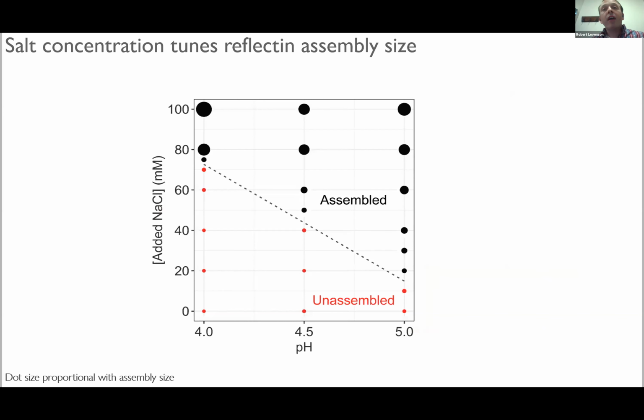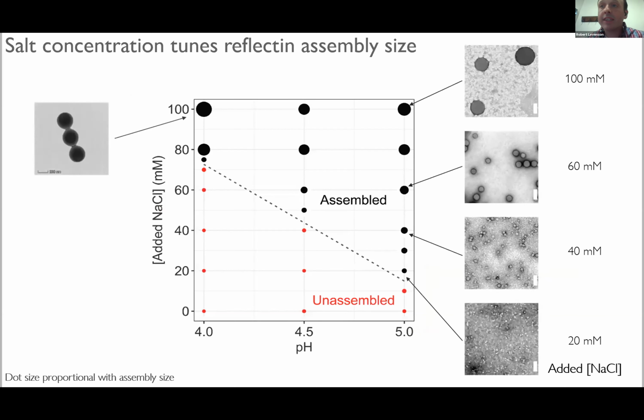At pH 5, if we dilute our monomeric protein with no salt into buffers with increasingly more salt, and we characterize those, we get spheres that are progressively larger with more salt. In this case, these assemblies are size stable over time. They do not continue to grow as we add salt. And so, analogous to the pH neutralization assay where we increasingly neutralized the protein and drew larger assemblies, here, again, they are spherical as well. So similar morphologies to those seen by the pH neutralization assay.